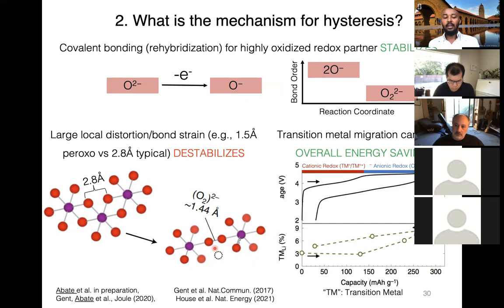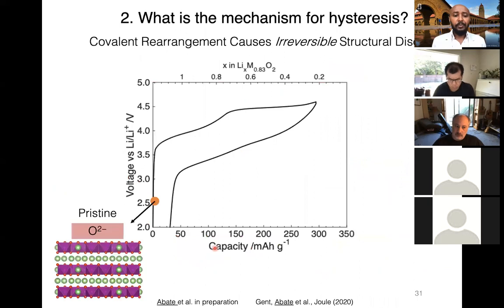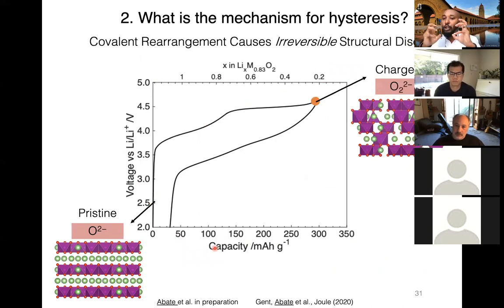the peroxide formation. So we can actually summarize this understanding in a very simple schematic, as shown over here. What happens in the pristine state is that we have a layered system in the form of an oxide O2- state. Upon anionic redox and upon charging, we form a short covalent bond with a bond length close to 1.4 angstrom. And this is accompanied by a cationic disorder to alleviate the bond strain. Therefore, this leaves us a very disordered material. Therefore, the path one would follow moving from left to right is very different from the path one would follow moving from right to left, because we have different structure points for the two pathways.